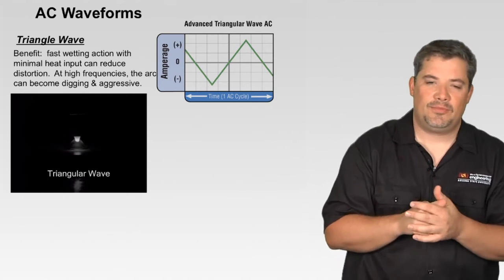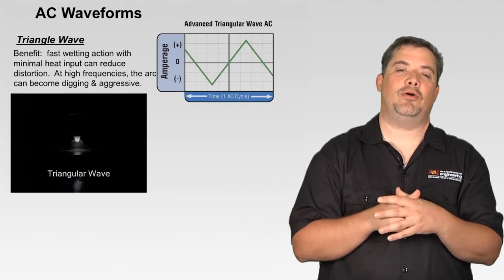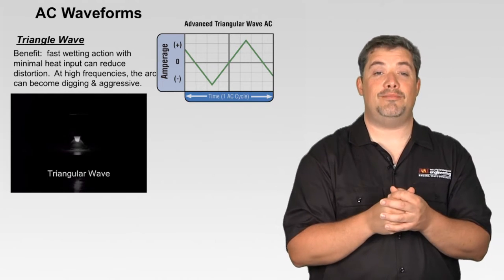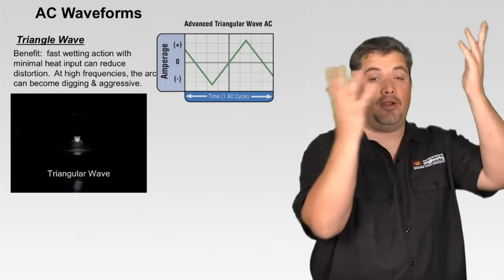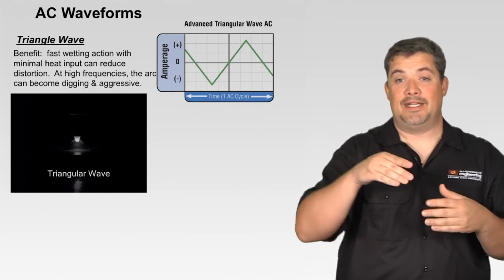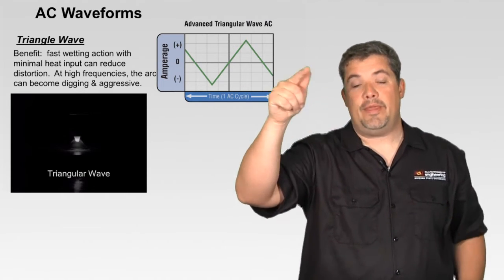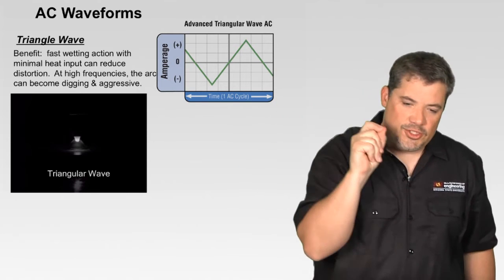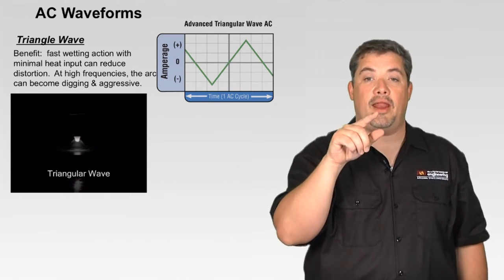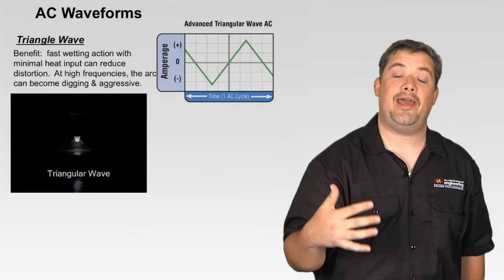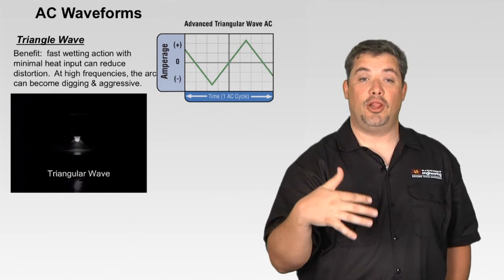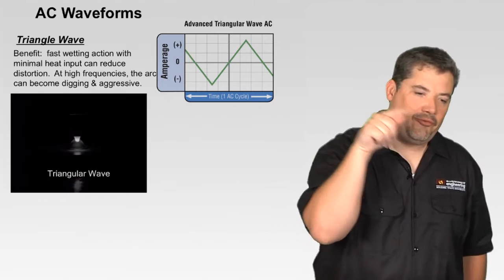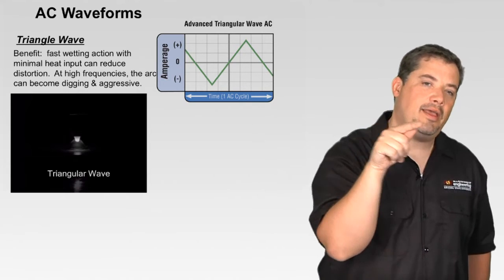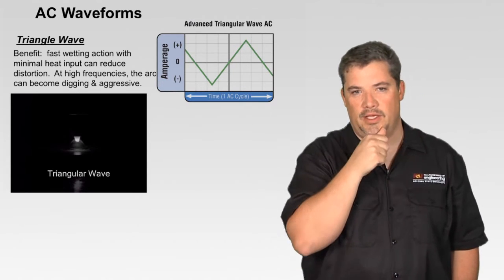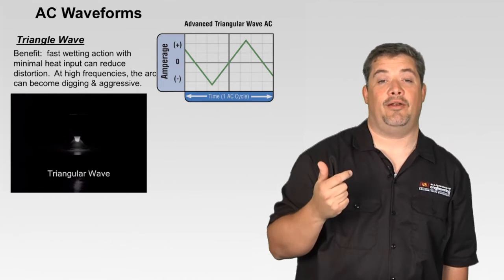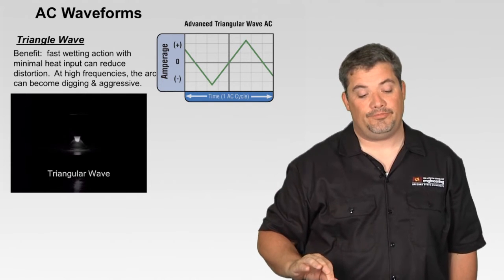They would take 10 to 20 of these tests to get one right. But with the triangular wave, it actually makes it so easy they can just get right on it and they're done. It's a beautiful thing. So that instant that it goes to that peak amperage, if you will, it's just enough to punch it into that corner. And being that triangle shape, there's a lot less energy there. So we lower our heat input, but we get the benefit of that quick punch of high amperage to just get in there quick. And again, at very high frequencies and higher amperages, it becomes digging and aggressive.